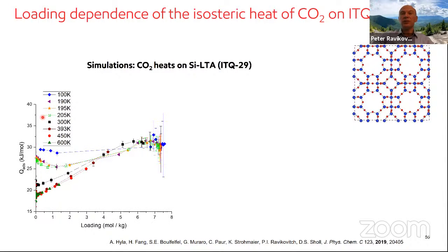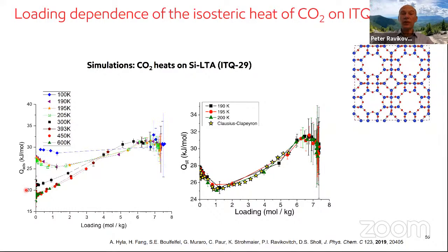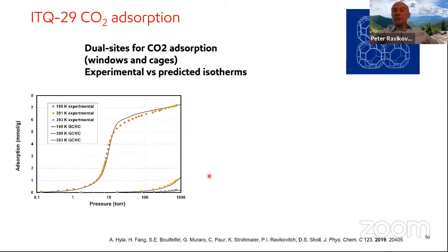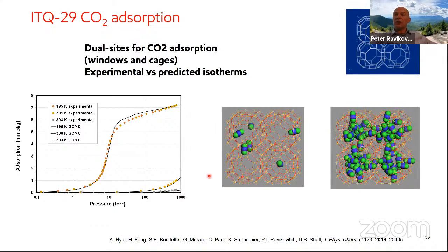These are more detailed simulations for CO2 in siliceous LTA. Now we consider it as a function of loading and at different temperatures. And you can see at higher loadings, the heats are pretty much temperature independent, but at low loadings, there is a very substantial temperature dependence. Again, if you take this rather interesting non-monotonic curve at around 195 K, we did very careful simulations and we checked by Clausius-Clapeyron that this is indeed the case. So experimentally, we have nice agreement between experiment and predictions.